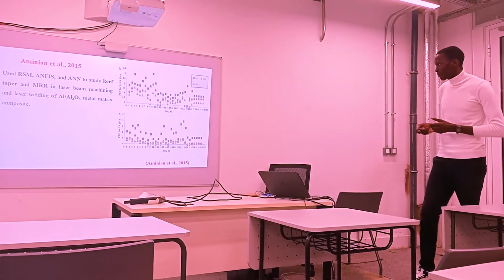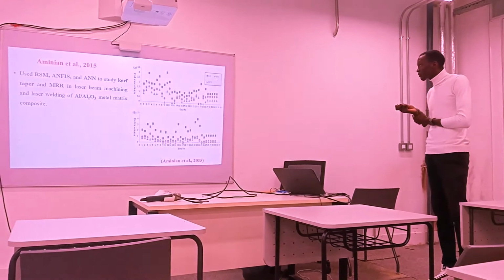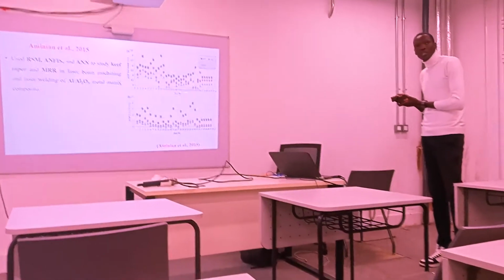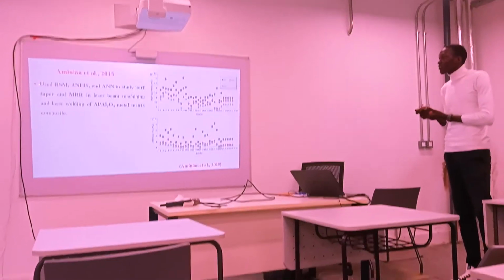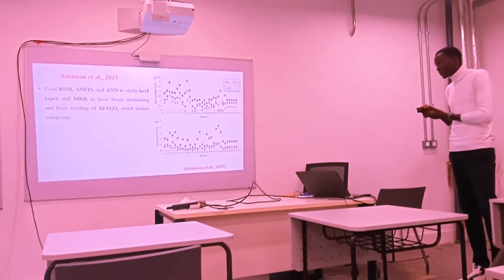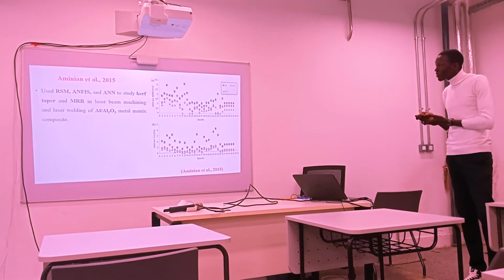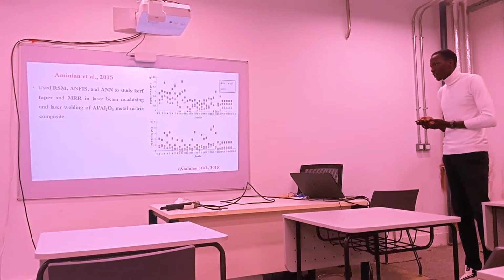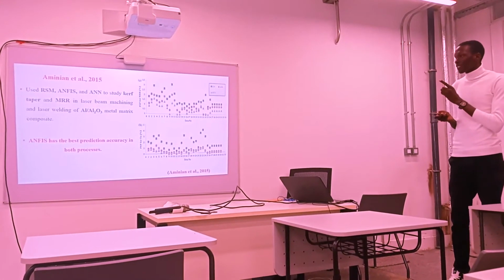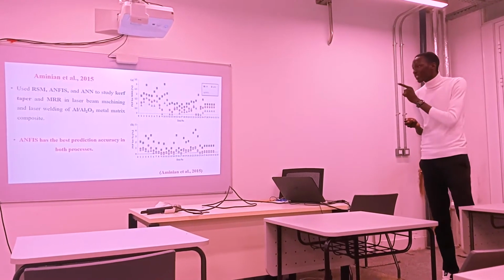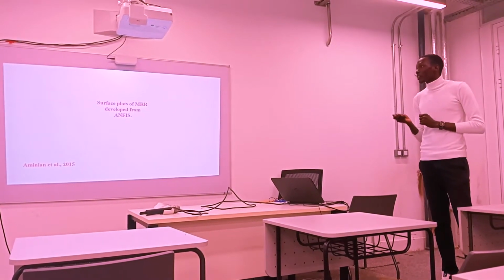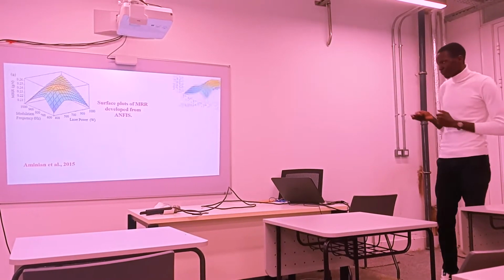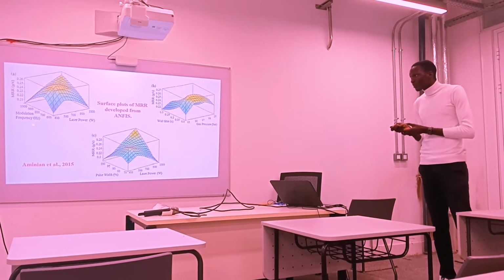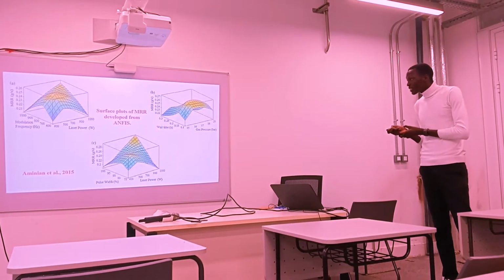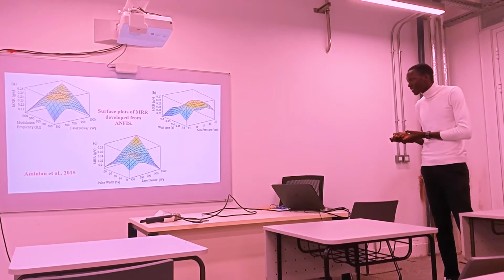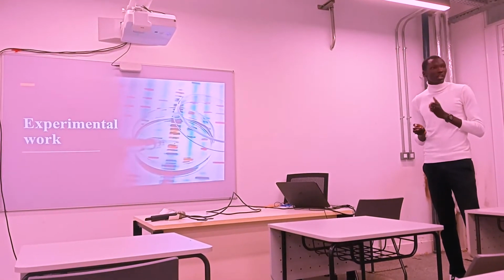This is the percentage error for the three methods. You can see that for ANFIS, which is green, the values are the smallest compared to response surface methodology and ANN. This is for material removal rate, and this is for kerf taper. Then they concluded that ANFIS, which is what we used, has the best prediction accuracy in both processes. Now, they produced some wonderful surface plots. As we can see, this is modulation frequency against laser power, the wait time against gas pressure, and the pulse width against laser power.